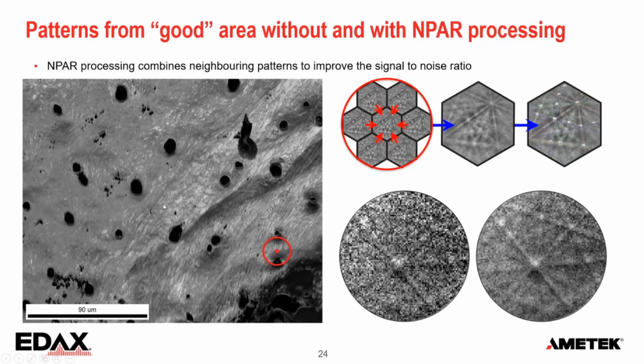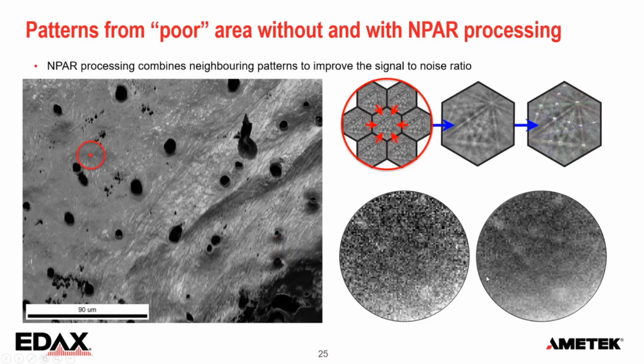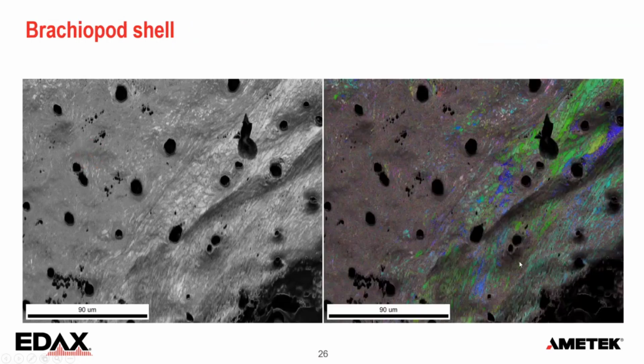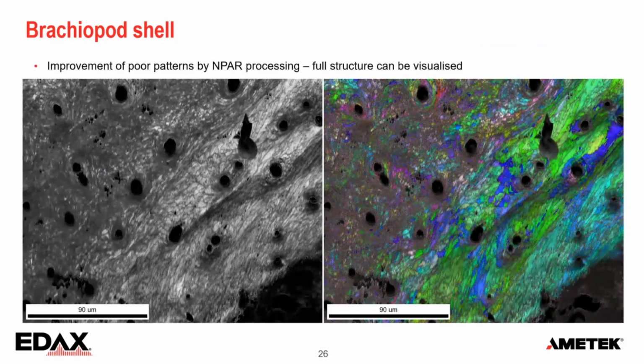And if we do the same trick on the top left, then this is what we get. With a bit of imagination, you can see where the zone axes are on this pattern here on the left. But after NPAR, we can actually identify some of the bands. And in this material, that is enough for indexing. And then we go from this indexing result to this.